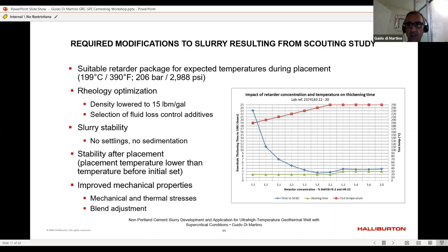During the optimization, it was deemed necessary that the behavior of the non-polymer stabilizer in the design at test conditions needed to be mapped, especially regarding viscosity at surface as well as in downhole conditions. Mixability, viscosity, and pumpability of the slurry depend on delayed hydration of the non-polymer stabilizer, while the heat exposure will counteract thermal thinning and stabilize the slurry downhole. This resulted not only in an ideal concentration, but also in a recommended mixing procedure.